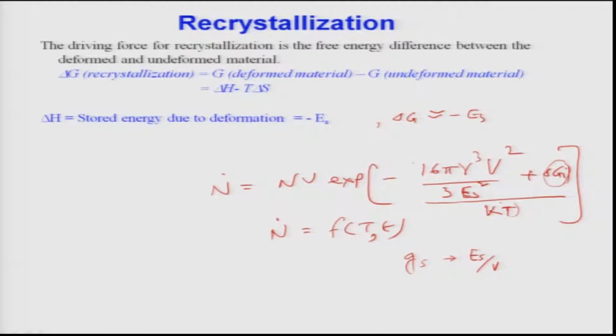It's just like the nucleation rate in classical solidification. If you plot nucleation rate versus undercooling, after some point it shoots up, it increases rapidly, and exactly the same thing happens here, because it's an exponential of minus 1 by T terms.